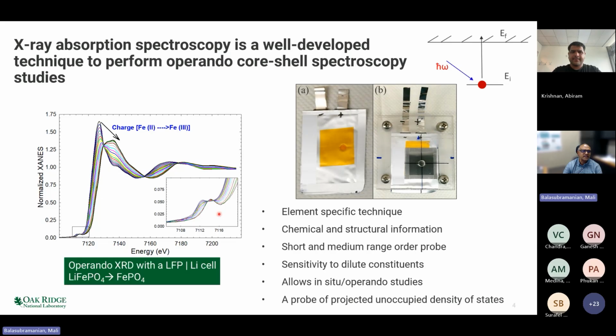The pre-edge region directly monitors the available unoccupied density of states of a particular angular momentum character. In the case of K-edge spectroscopy, you are exciting a 1s electron from the interior of an iron atom into unoccupied d orbitals. The d orbitals are the ones which are involved in chemistry in 3D transition metals.